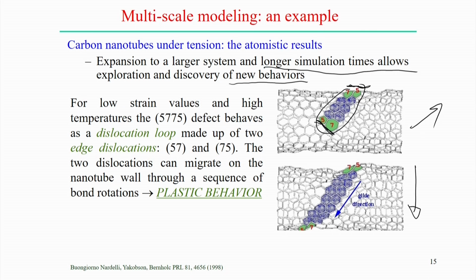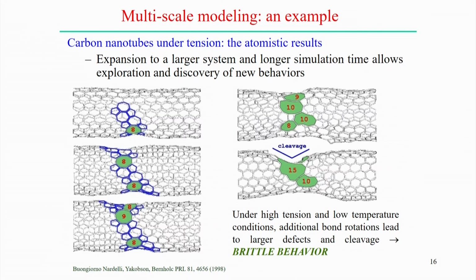Specifically when the carbon nanotube is subjected to some kind of tensile force. Now, if you look into the carbon nanotube under tension, the atomistic results, but with expansion to a larger system and longer simulation time, we see that under high tension and specifically low temperature conditions, the additional bond rotation finally leads to larger defects and cleavage. That finally relates to the brittle behavior of the carbon nanotube.